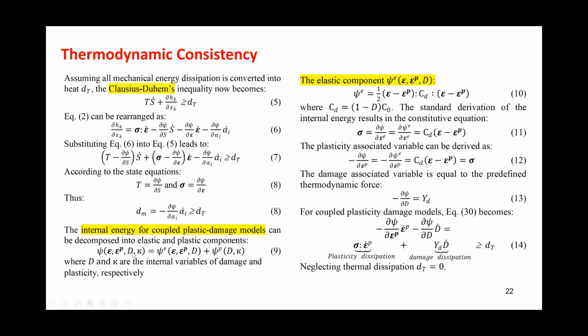We can also divide the total strain energy, or our internal energy, into an elastic and a plastic component. Okay, so the elastic is a function of the total and the plastic strain, and the plastic is just a function of the damage and some internal variable. The elastic energy is given by this, the damaged material multiplied by the elastic strain, which is the difference between total and plastic strain. We could show that the derivative of the strain energy with respect to the elastic strain gives us the stress, and that should be a product of the damage constitutive relation and the elastic strain.